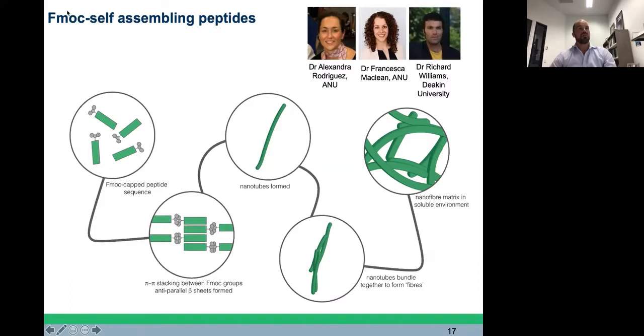So what we do is we have this FMOC protecting group, this aromatic group on the end here, and then we assemble this IKVAV amino acids here, and then at high pH, these are charged and solubilized, so they're sort of floating around in a liquid. And then we use a pH switch, so we just lower that pH down, and what we get is this sort of pi-pi stacking of these aromatic FMOC groups, and then you get beta sheet formation between your amino acids, and they roll up and they form these sort of hollow nanotubes that you can see here, that then bundle together to form this sort of fibrous scaffold, similar to what I showed on the previous slide, but as an injectable hydrogel. And the real beauty of this system is that you shear it, so we shake it in the clinic, and it turns back into liquid, you inject it, and it reassembles in situ. So it's sort of a smart system.